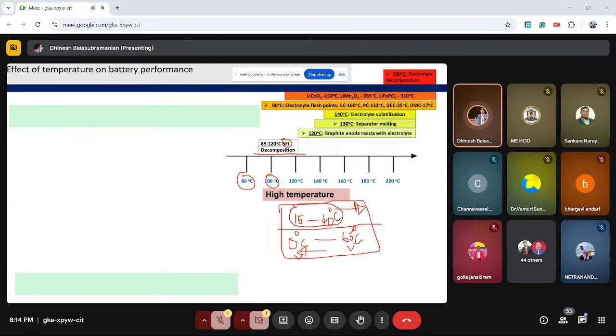When you try to open the pathway for electrons to move in the horizontal direction, it would directly result in short circuiting. What actually happens in all the high temperature conditions is that you will always try to create a pathway for the movement of electrons in the horizontal direction. This solid electrolyte interface layer is a strong barrier to repel the movement of electrons in the horizontal direction. But after the entire battery pack or the cell temperature is close to 85 to 120 degrees Celsius, it decomposes the solid electrolyte interface layer. So slowly what happens is it opens the pathway for electron movement in the horizontal